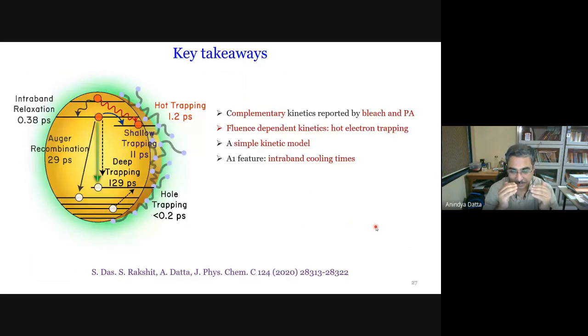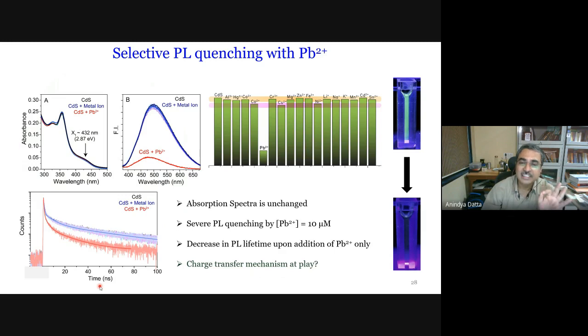The very careful and backbreaking analysis of the transient absorption data yielded the time constants associated with all the processes that take place post excitation, and to give credit to Sharmishta for doing all of this. The other thing that we observed is we wanted to know, is it possible to modulate, because remember the theme of our work is light emission at will as per order. So can we quench this emission by specific inputs? And we found that among the metal ions that we studied, only lead can quench the photoluminescence of these cadmium sulfide nanoparticles at concentrations as low as 10 micromolar.